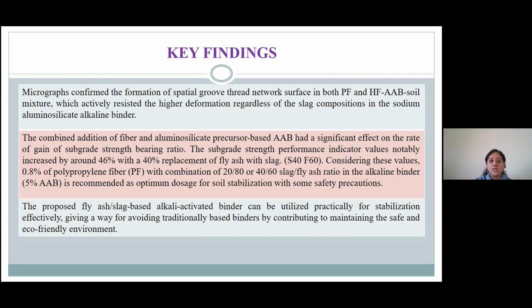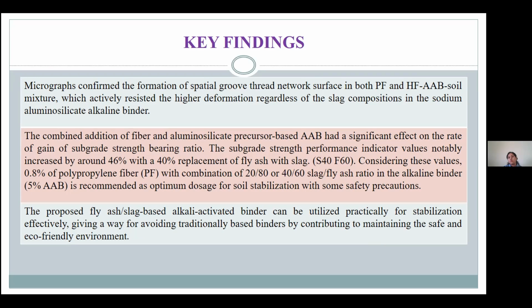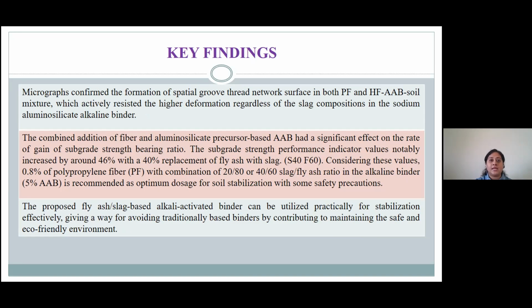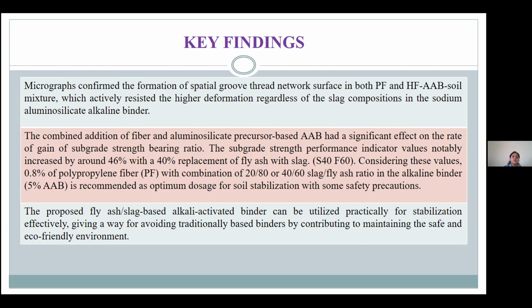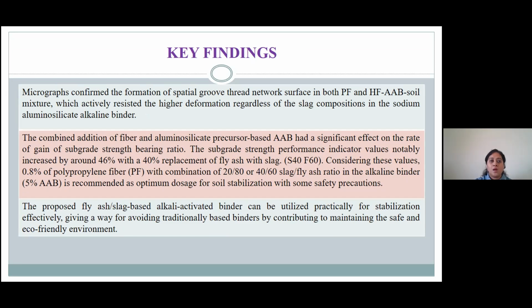We found that the optimum combination is 60% fly ash and 40% slag, with addition of AAB in the range of 5%, and we can use 0.8% fiber. So in conclusion, this proposed fly ash or slag based alkali activated binder can be utilized practically and effectively, giving a way forward from traditional binders, and this method is sustainable and a more eco-friendly solution.